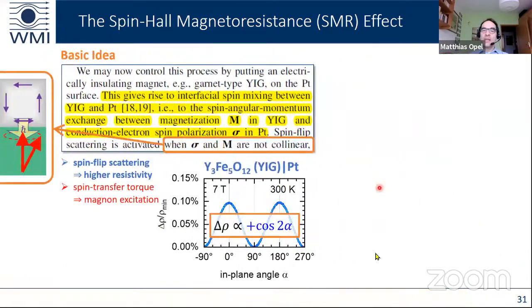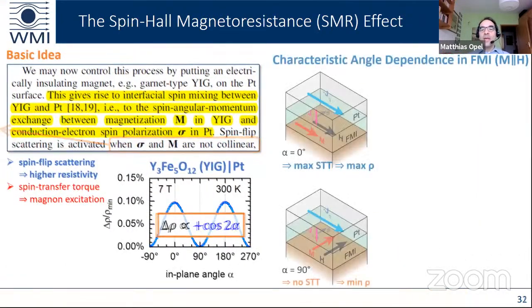So how does this look? We apply a magnetic field H. The magnetization M follows the magnetic field H. We apply an electrical current J, and this electrical current in the platinum produces this spin polarization S at the interface. Here, S and M are perpendicular to each other. We get the maximum spin transfer torque and the maximum resistivity.